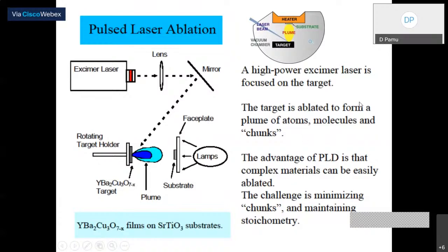The target is ablated to form a plume of atoms, molecules, and chunks. You see, it will come and hit the surface, and it is forming a plume. That means it will melt the top layer of the material and bring this material to sit onto the substrate. It will not decompose the material. It will take a small chunk, a small piece of the surface layer of the target, and bring it here. But in sputtering, you are completely bringing every molecule, every metal or metal oxide, into the molecular form and bringing it onto the substrate. But in the case of PLD, pulsed laser ablation, what are you doing here?